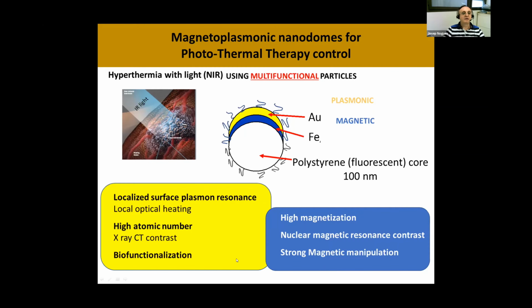What's the magnetic layer giving us? Since we use iron, it has a high magnetization. It also has a strong nuclear magnetic resonance response, which can be used as MRI contrast. And since it has a high magnetization, it's very easy to manipulate it using magnetic fields.